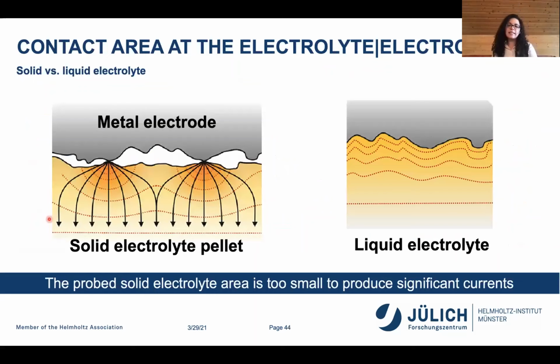When we were looking at this, we were wondering how the contact areas at electrode-electrolyte interfaces look when solid versus liquid. In the case of a liquid electrolyte, it conforms to the roughness of your contact metal electrode. Whereas in the case of a solid electrolyte, you have an intrinsic roughness of your solid electrolyte pellet as well as the metal electrode. And usually the probed area is just too small. And this could lead, if one were to do an electrochemical measurement, to misinterpretation of data.